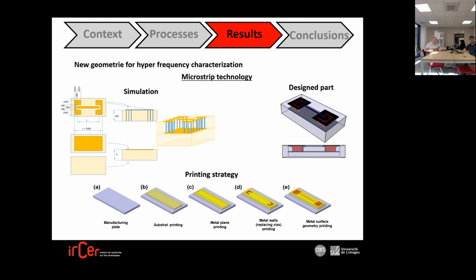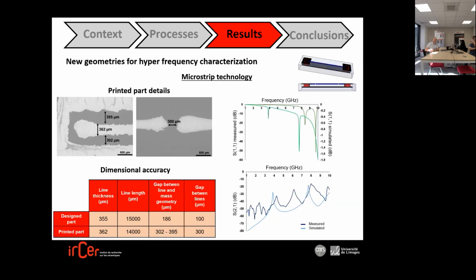At the bottom of the slide, you can see the printing strategy that has been developed. First, we begin with the manufacturing plate. After, we print the total alumina substrate. Then we clean the top of the substrate in order to print the metal plane. After, we print the metal walls that replace the original vias. And then at the top of the part, we print the metal surface geometry. Here, you have some pictures that show what has been printed.